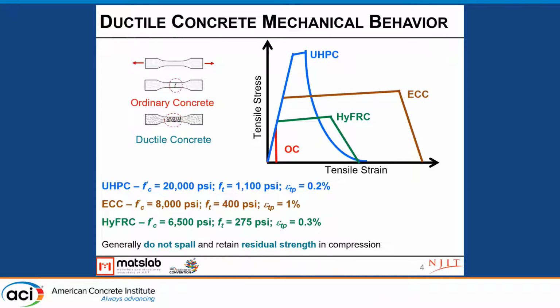We can all understand why we say ductile concrete system. It's mainly because of the behavior of these materials in tension and flexure. The other main difference, as you can see here at the left, is the cracking behavior of these materials. In ordinary concrete, we usually have a crack in the middle of a specimen, for example in flexure, that starts and gets bigger and bigger until we have the failure. But in ductile concrete systems, instead, we have multiple microcracks in different places of the specimen. And this can cause a big difference in the corrosion behavior of these materials compared to normal concrete when we are talking about the penetration of chlorides to cause corrosion.